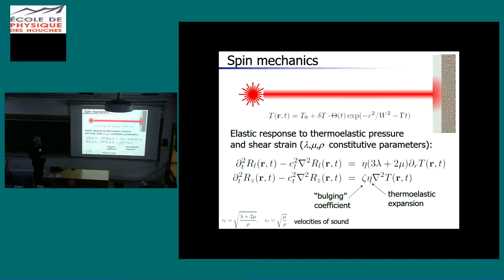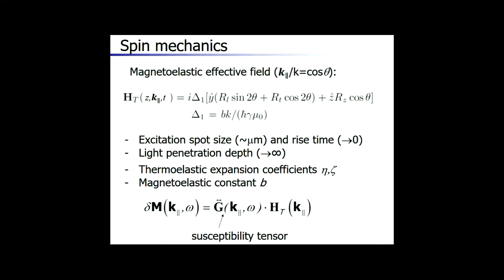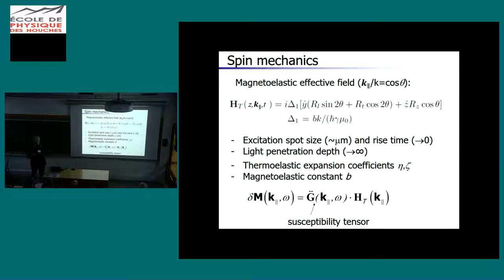Okay, so it's getting hot, and you have to solve the elastic equations of the system, which you can do separately for the transverse and the longitudinal ones, for the pressure and the shear waves. And what you need here are basically the source terms in this case. And the parameters are the elastic constants of the system. Now, because of the magnetoelastic coupling, these deformations, RL and RT, cause effective magnetic fields, which then act on the magnetization and cause the magnetization dynamics. Delta 1 here is the magnetoelastic constant, which is well known for YIG.